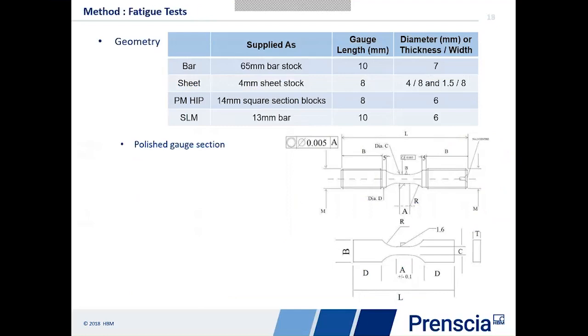So how about the fatigue tests then? Well, for the fatigue tests, we've used several different geometries. We've first of all taken as our background wrought material 65mm bar stock material, and we've also got sheet material as well. So these allow us to create, if you like, a background of what a wrought material fatigue property curve would look like. And then in addition to that, we've used powder metal HIP processing, so 14mm square section blocks for that, and selective laser melting, a 13mm bar.